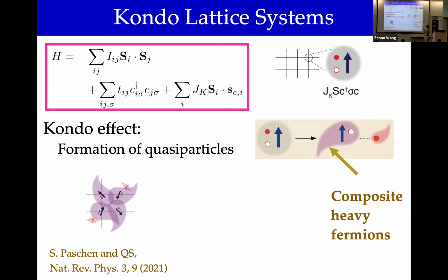So this object keeps track of the spins. There was a question of whether spins are impurities or spins are associated with a lattice. Spins are associated with a lattice. In the simplest case, there's one per site. So each spin is going to generate one electron excitation. And these are very sluggish. It has a hard time moving around, which is why in the end you have these quasi-particles, but they are very heavy. The velocity is extremely small.